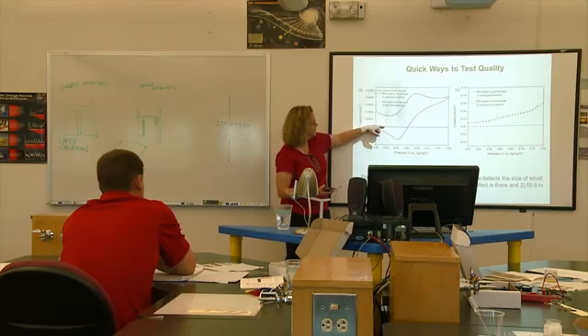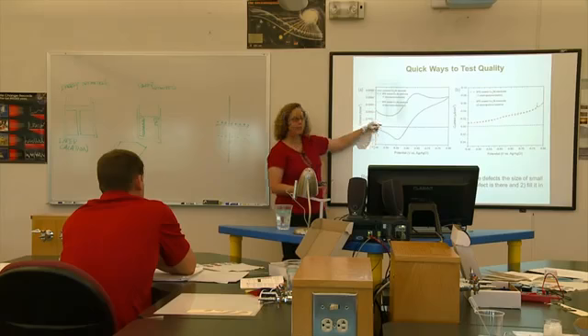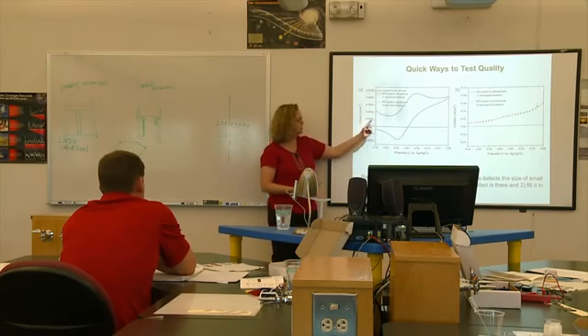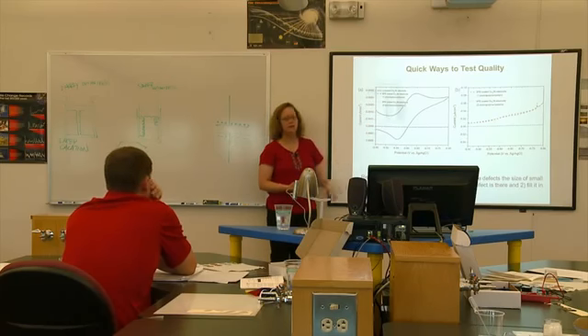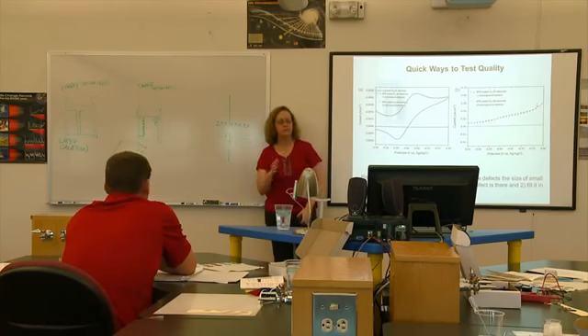And then these flat lines are what it looks like on our polymer after we've made it, which means there are no mistakes. We have really sensitive equipment. Notice the size of this current. We can actually go down to nanoamps, so we can go to 10 to the minus ninth. And it's super quick. This test takes 30 seconds.